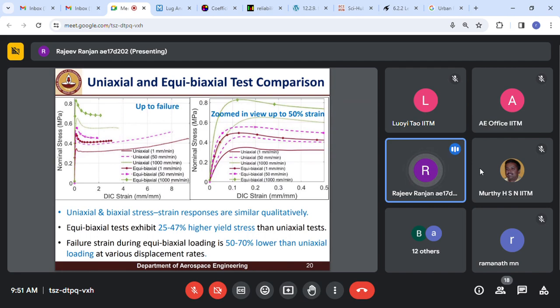This is happening because in uniaxial loading, one of the surfaces is free. Load is applied in one direction, and another surface is free to deform. So the material is offering less resistance. However, in biaxial loading, it is loaded in both directions, so there is no free surface. So the material is offering more resistance to deformation, leading to a higher yield stress. Also, it was observed that the failure strain during equibiaxial loading is 50 to 70% lower than that of the uniaxial loading.